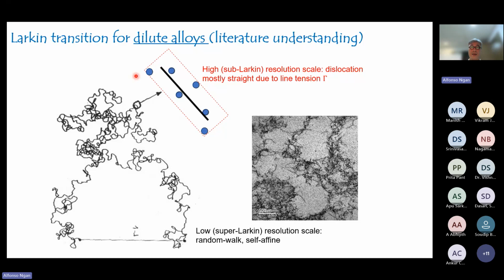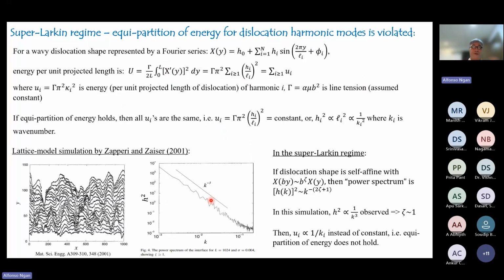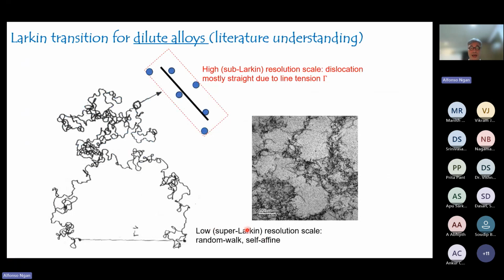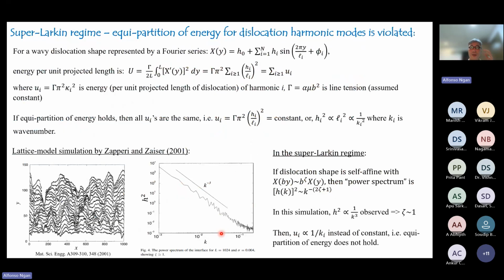So that's the so-called Larkin transition. That is, if you look at a dislocation shape using different resolution scales, there is a transition from being straight to fractal-like, from high to low resolution. So that's called the Larkin transition. Well, there are a few interesting consequences from the Larkin transition, especially if we look at the low resolution scale, the so-called super Larkin regime of the transition. One very important conclusion is that the equipartition of energy for dislocation harmonics would not hold in this super Larkin regime if the dislocation shape is fractal or self-affine.